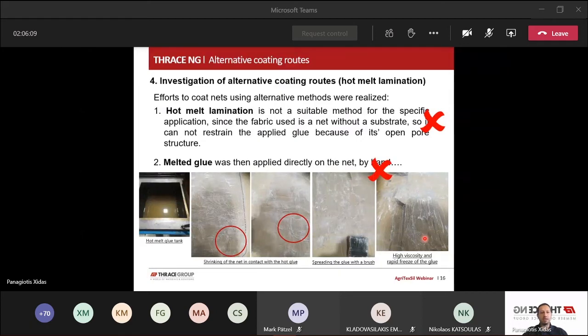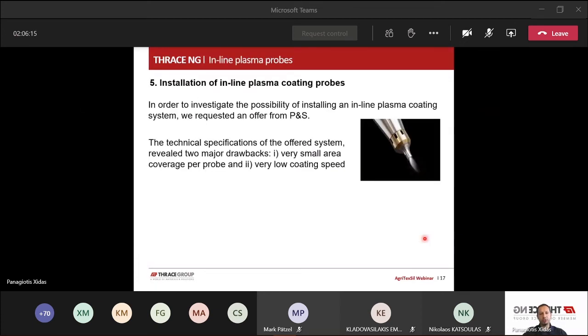So it seems that plasma treatment is a very well designed technique for this kind of applications. So we had to investigate the possibility of installing inline plasma coating probes. In order to explore that possibility, we requested an offer from our co-workers, the P&S company, but the technical specifications of the system revealed two major drawbacks. The first was the very small coverage area per probe and the very low coating speed.